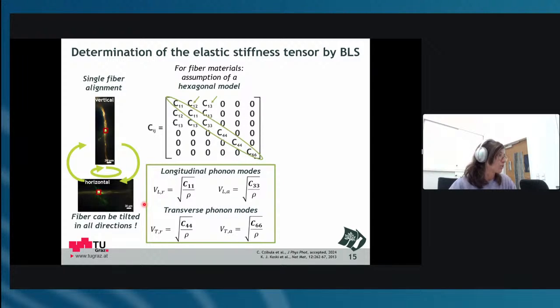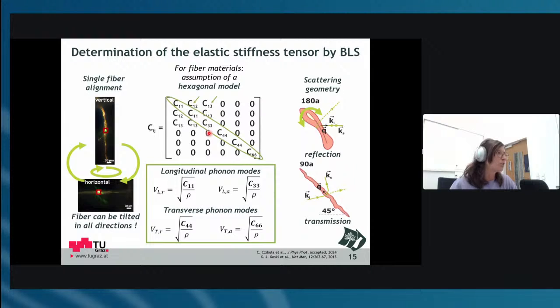So we have now the elastic stiffness tensor. We turn our fibers around, and then we try to determine as much as we can in this diagonal. And we do that with two scattering geometries. As I mentioned in the beginning, it's very important how you shine the light into your sample and how you get it from your sample to the spectrometer. And there are two main scattering geometries, at least what I have been using.